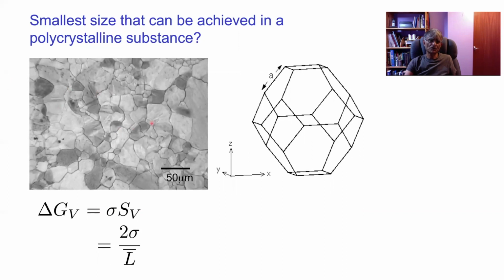This is a grain structure, and I explained to you in an earlier lecture on pearlite that the cost of creating these boundaries here is the surface per unit volume times the interfacial energy, a grain boundary energy in this case. So if I multiply these two, I get 2σ over the mean linear intercept as the cost of creating these grain boundaries. And that cost has to come from somewhere, okay? It's provided by the free energy change from austenite to ferrite.